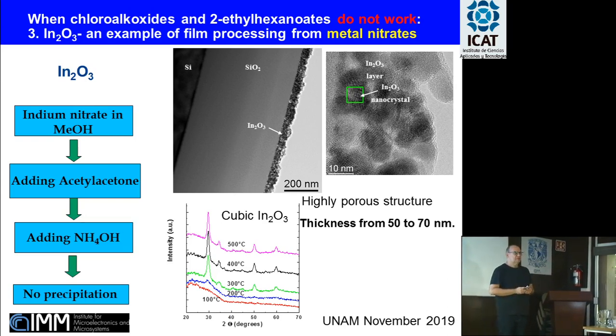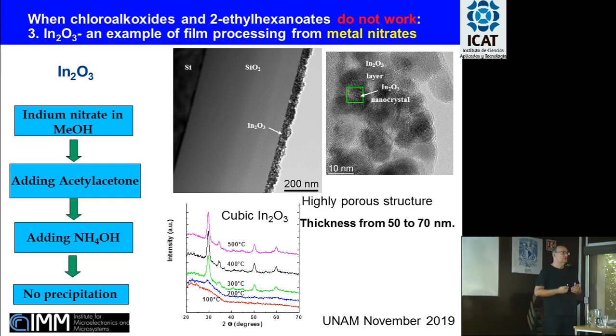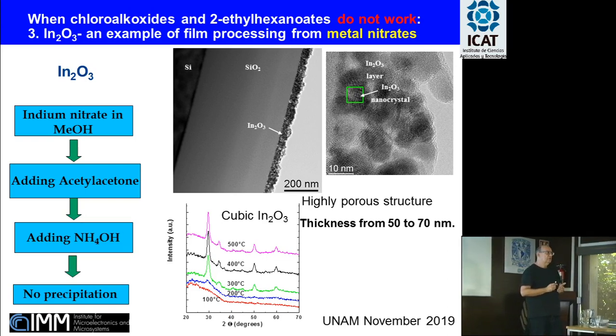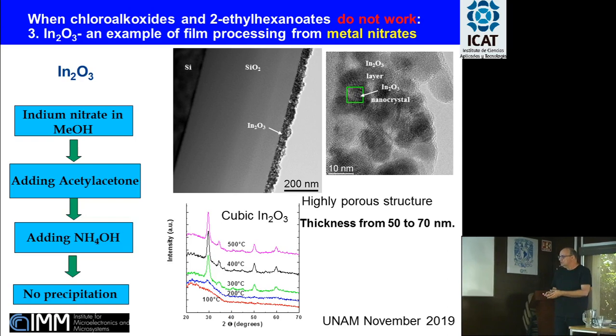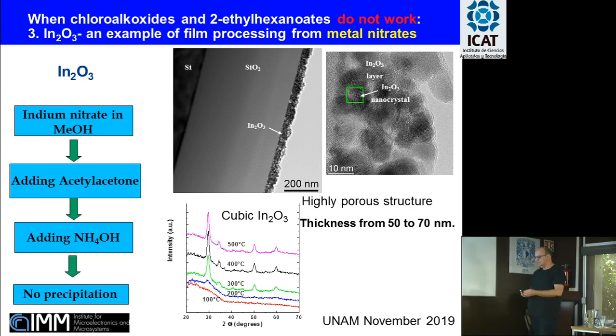You can dissolve a precipitate by adding some acid, but we have observed that in this case, making thin films from solutions prepared from precipitates is not so easy. They are not so uniform in general, and they do not have a very good adhesion to the substrate. So this procedure to prepare a modified indium oxide solution was useful for avoiding precipitation and for making a uniform film, which is also very porous. You can see the indium oxide nanocrystals inside the film structure. And once again, we have the typical cubic structure of indium oxide, its final crystallographic phase.